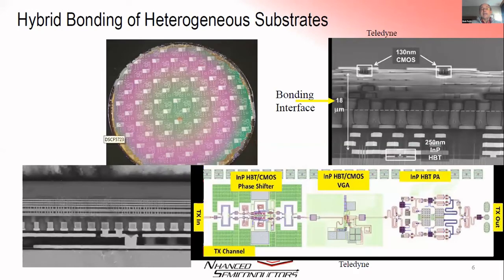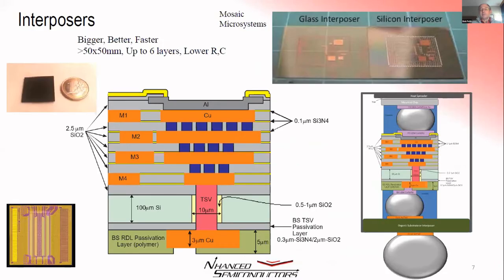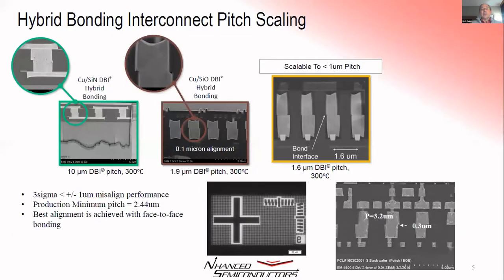And by the way, the leading edge of that technology, I go back to it, we have built things now for customers down to 0.8 micron pitch. That's below what we feel comfortable commercially producing, because our technology is really limited to about plus or minus 1 micron. But as a proof of existence, the technology is certainly scalable well below 1 micron pitch.